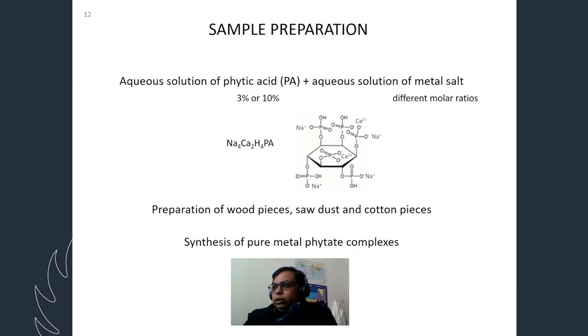After we made the solutions, we dipped our material like cotton, sawdust, or wood pieces. Cotton we dipped for 1 minute, then took it out and dried in air for at least 1 day. And we measured how it's drying. We measured the weight of the sample from time to time for 6 days. And we saw after 1 day, the sample became quite okay, meaning it loses its water content. So increasing drying did not show a big effect in the flame retardant process.